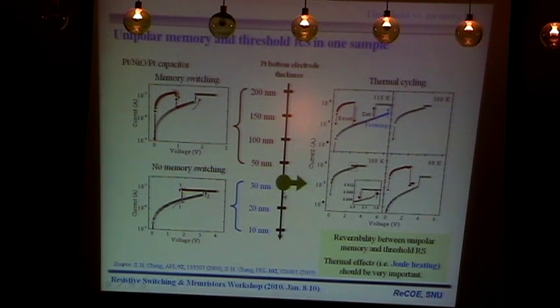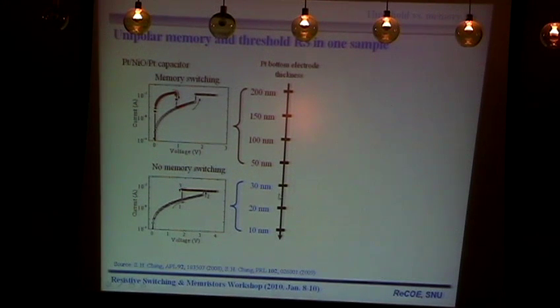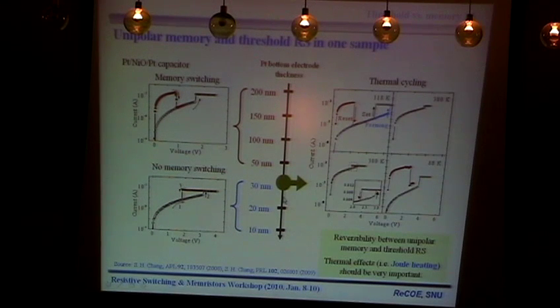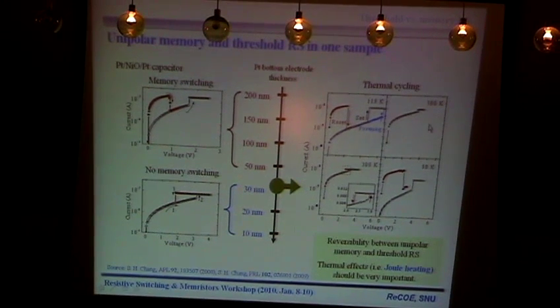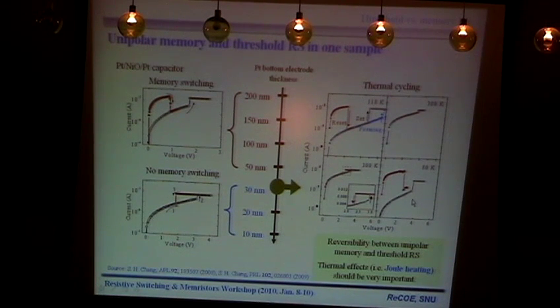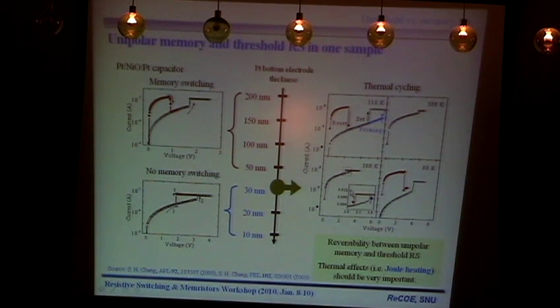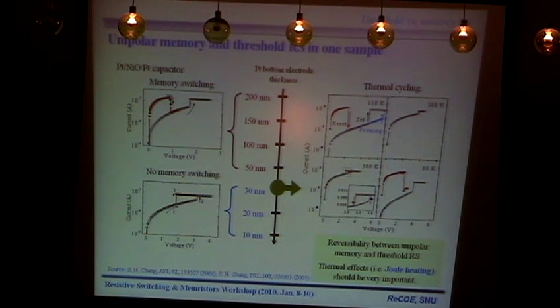Also, he picked this 30 nanometer bottom electrode sample, and originally it shows threshold switching, but if it cools down, memory switching recovers. Then warming again, threshold switching; cooling down again to 80 Kelvin, memory; and threshold, and so on. So it's somewhat cyclical. This indicates that there should exist some kind of reversibility between unipolar memory and threshold resistance switching. This indicates that maybe memory and threshold switching come from the same origin.